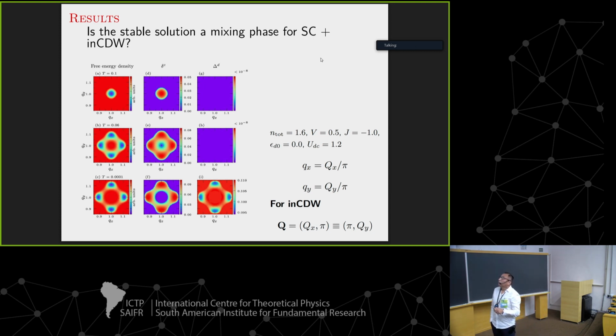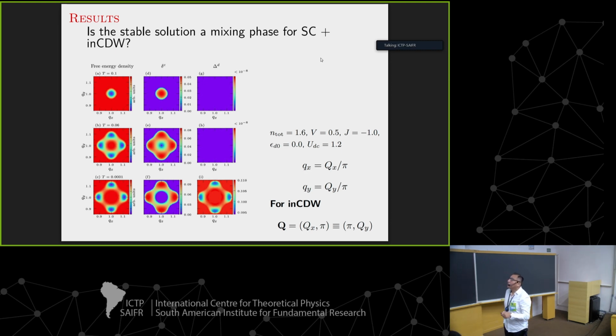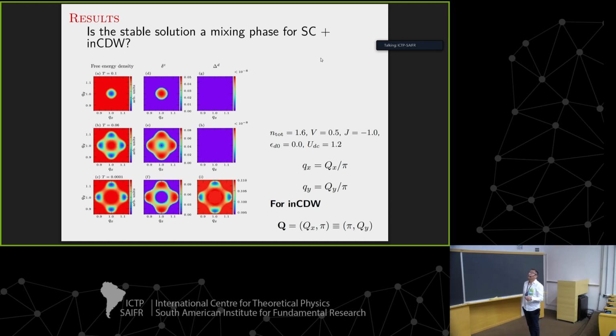So, starting from this panel for this temperature, we see that the most stable solution, the minimum of the free energy density, is just around Qx 1 and Qy 1. So it is, for us, indicating that a commensurate regime is established, okay? This result can be confirmed from the charts, from the CDW order parameter analysis, and you can see here, we can observe that we find very robust values of the CDW order parameter. On the other hand, from the analysis of the superconducting order parameter, we see that this is mainly 0. So from this first row here, we can conclude that our model predicts a commensurate charge density wave phase, at least for this temperature.